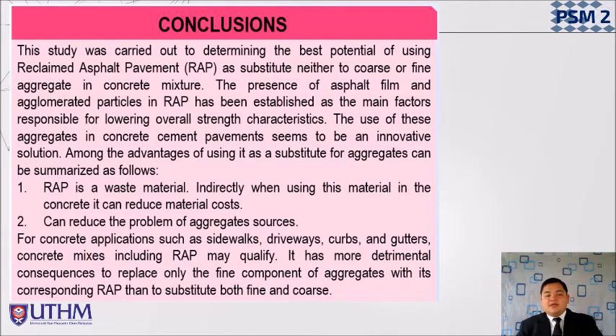Alright, we have come to the final chapter, which is the conclusion. This study was carried out to determine the best potential of using reclaimed asphalt pavement as a substitute for either coarse or fine aggregate in concrete mix. The asphalt film and agglomerate particles in RAP have been established as the main factor responsible for lowering the overall strength characteristics in the concrete mixture. The use of this aggregate in concrete seems to be an innovative solution. Among the advantages of using it as a substitute for aggregates can be summarized as follows.